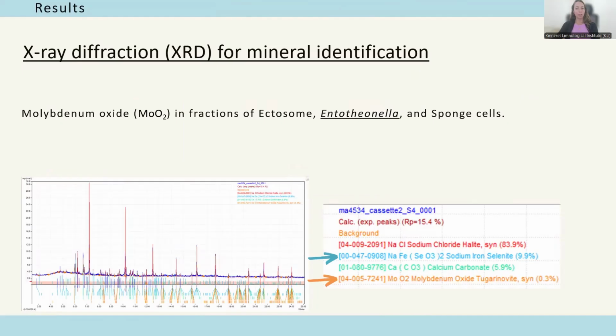To connect this intracellular evidence with the bulk mineral data, we return to XRD. The XRD analysis detects molybdenum oxide in several fractions, including the Entotheonella fraction. This supports the presence of molybdenum-bearing crystalline material in the bacterium-enriched fraction. However, the intracellular spheres observed by TEM did not produce a clear crystallographic signal. Therefore, XRD and TEM-EDS should be interpreted together. XRD tells us that crystalline molybdenum oxide exists in the fraction, and TEM-EDS tells us that the molybdenum-rich spheres exist inside Entotheonella cells. The exact phase inside the intracellular spheres remains unresolved.